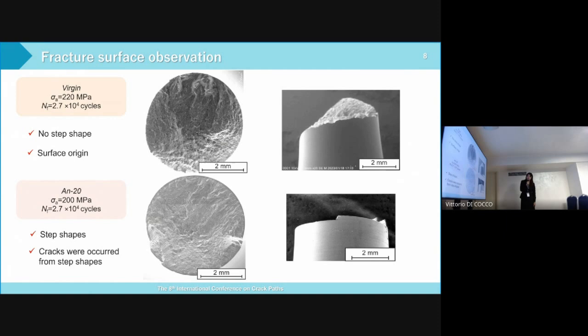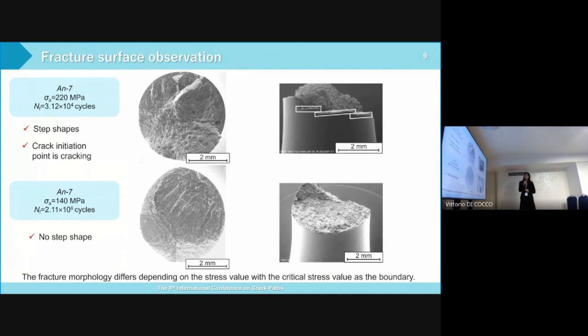Next, regarding AN20, step shapes were observed on the side view, and it was confirmed that the cracks occurred from the step shapes. Since the step shape is linear, it is assumed to be brittle cracking, and is considered to be cracking of the anodized film. Next, this is the result of AN7.